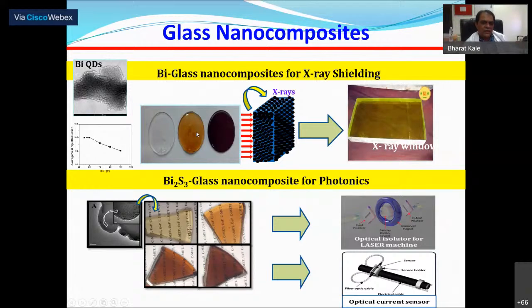Generally, lead glass is used for X-ray absorption, but we have proved that these small nanoparticles of only 1 or 0.5% in the glasses can absorb all kinds of X-rays and gammas. And we can have glass windows. This glass window can absorb the gamma rays and X-rays. We have taken a US patent on this.